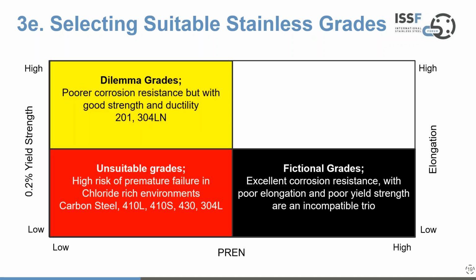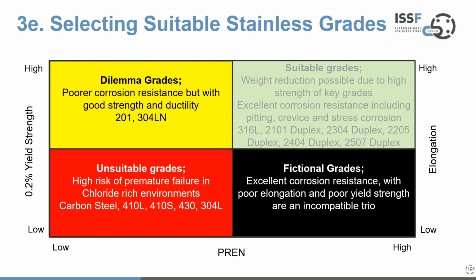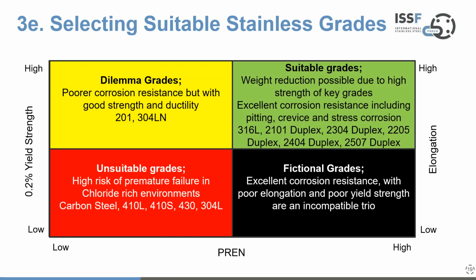You then have, in the top left, the dilemma grades. Still, the corrosion resistance is not great, but you have good strength and good ductility. And here you see the manganese austenitic grades and the 18-8 doped with nitrogen to improve strength. But then we get to the final box. What I would say is really the suitable family of grades. This is where you get the possibility of significant weight reduction due to higher strength, excellent corrosion resistance, including resistance to the classic 3 corrosion mechanisms. And you have broadly the duplex family and the higher alloyed austenitics in this box. So that's really the target box when you're thinking about structures that are load carrying and also in corrosive areas or corrosion environments.